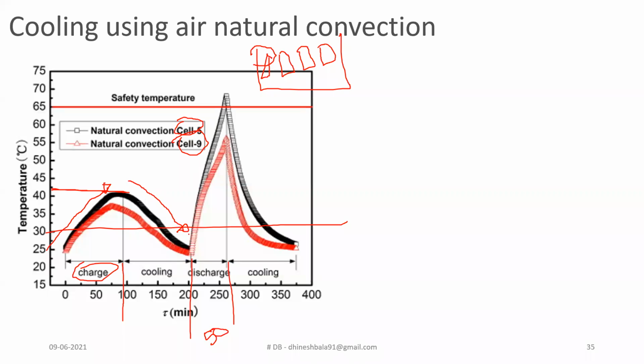But at the time of discharge, it exceeds to a greater extent. And the safety limit, which I mentioned earlier, is 65 degrees Celsius. The lithium ion battery safety limit varies from 60 to 65 degrees Celsius. In this particular case, cell number 5 exceeds the safety limit of the lithium ion battery when you are just dealing with natural convection. And this is for one particular study.